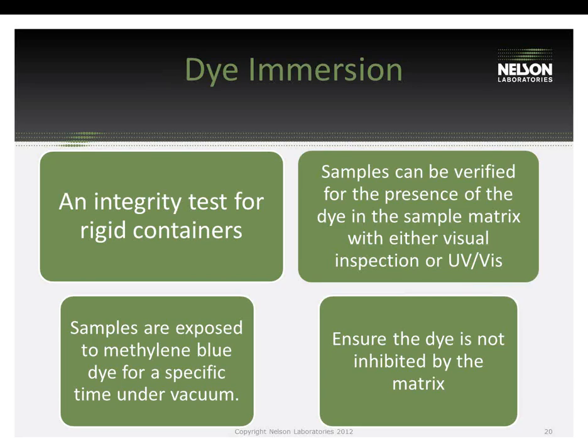The next option is dye immersion. This also uses a blue dye, and it is a test for rigid containers. If you have pharmaceutical products or syringes, this is an option for you. And the way that it works is we place the samples into a blue dye, and we put it under a vacuum for a specific amount of time. After that time's elapsed, we release the vacuum, and with the release, if there are leaks in the product, it will draw the dye into the sample. Now you can test those samples by either UV-Vis, or you can do a visual inspection. Normally we would do visual inspection for just R&D purposes, and then for routine production we would go with the UV-Vis because it's a lot more sensitive.